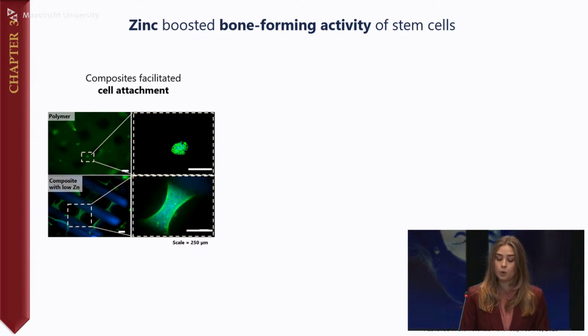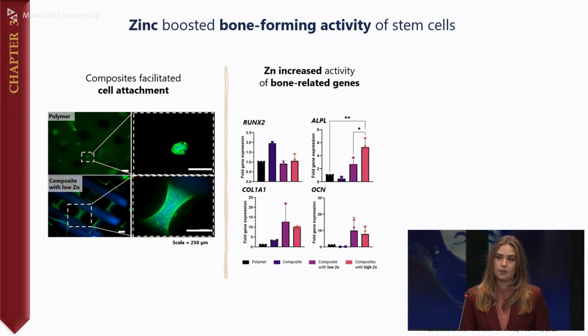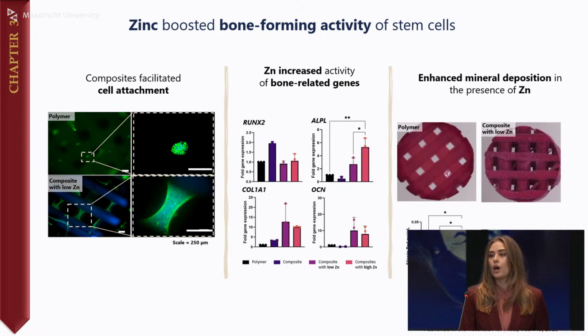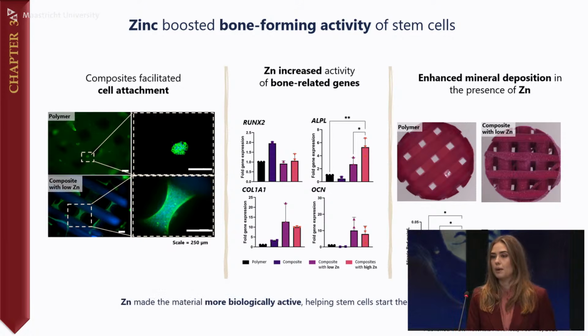What we saw next was even more interesting. We saw that materials containing zinc didn't just support the cells, they actually gave them a little push to start behaving like bone-forming cells. We could see higher activity of genes involved in the bone formation process, and later on, we saw enhanced mineral deposition in the presence of zinc. And this led us to a conclusion that addition of zinc really made a difference. It made our materials more biologically active, and it gave the cells a little push to start the bone building process.